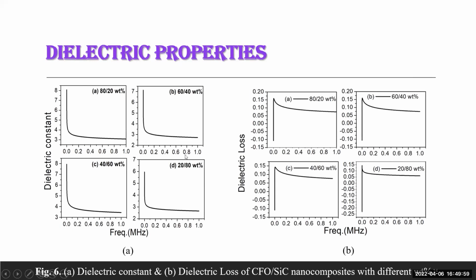As we can see in the figure, we got the highest dielectric constant and loss at the initial frequency, but as we increase the frequency, the dielectric constant and loss started to decrease, and after a certain frequency they became constant. It might happen due to the saturation of polarization among the atoms. So these are all the properties we have characterized for the material.